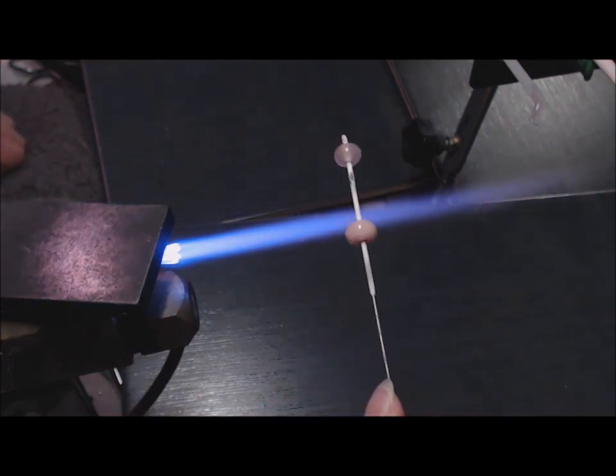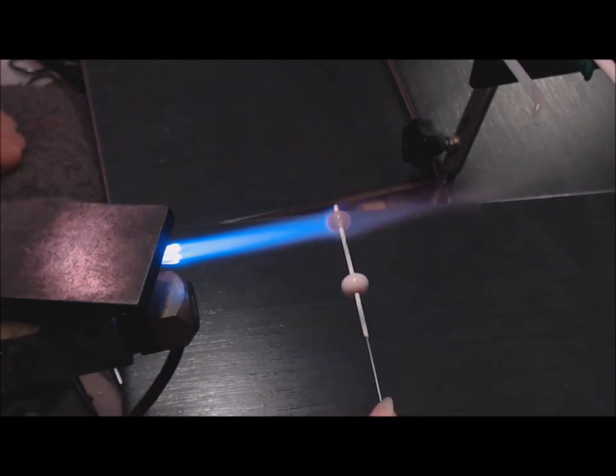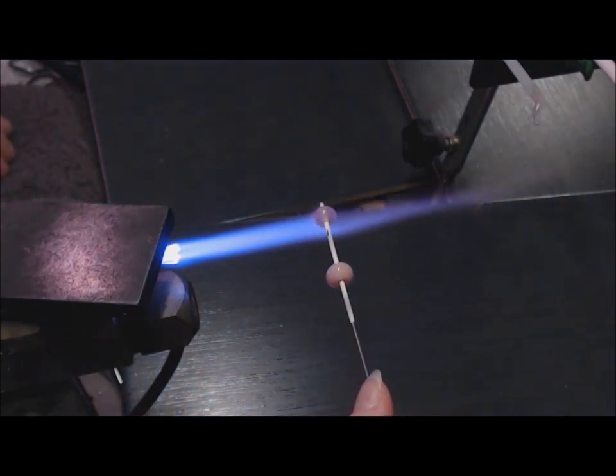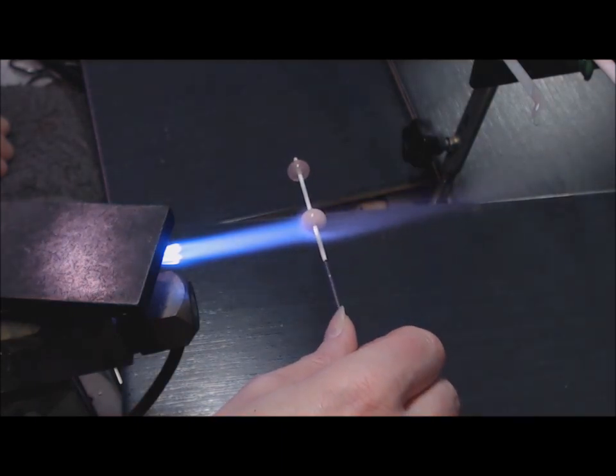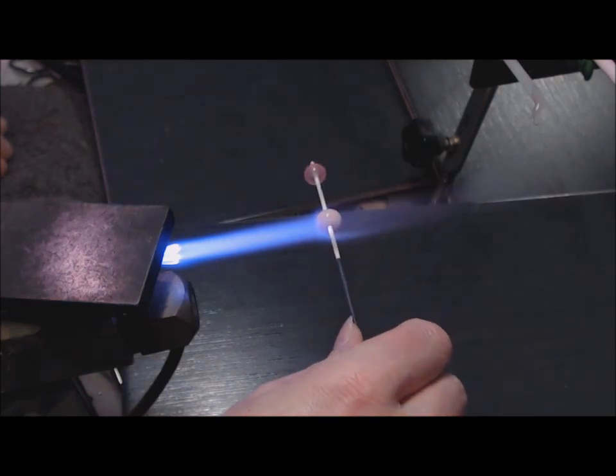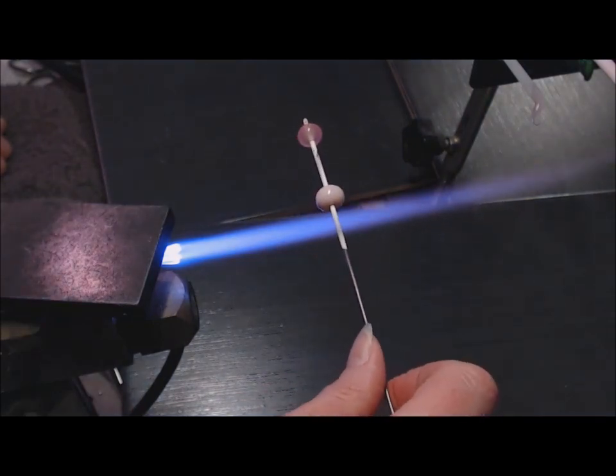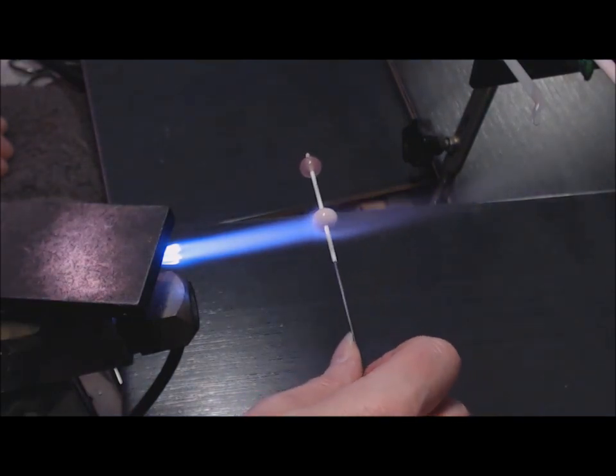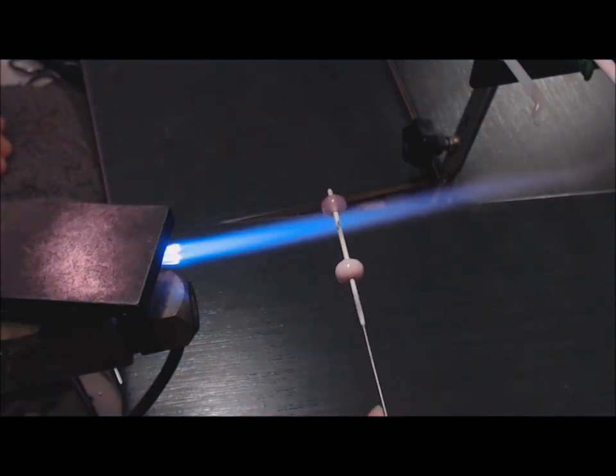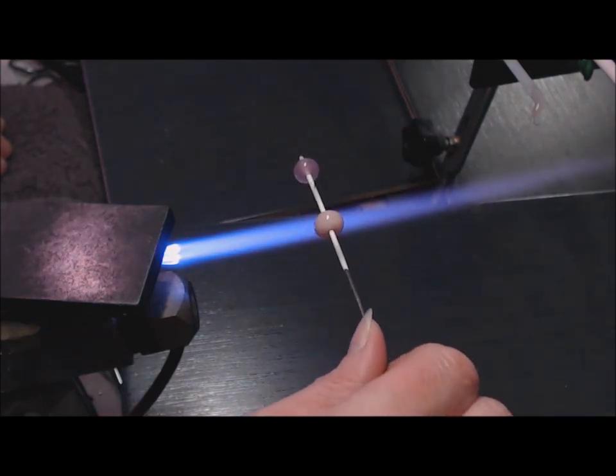So it's not a very reproducible process in that you won't easily get the same color twice with the opalinos, because the color will intensify with the time the bead spends in the kiln, and it will also become more opaque. And so different beads made at different times during your bead session will be different colors when they come out of the kiln. It's not necessarily a problem because I like color variations, and I find that it gives a little bit more life to a bead set. Not all the beads are exactly the same colors. Just know that it's not always very reproducible though.